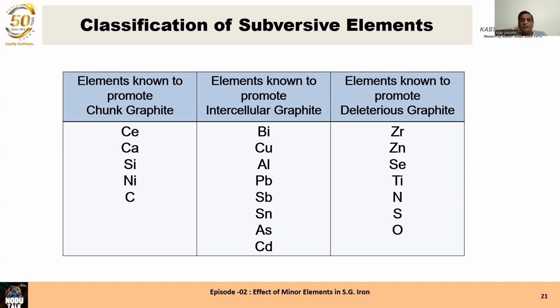Then the elements which are known to promote deleterious graphite, graphite which is affecting the mechanical properties, ductility and all the good properties of SG iron, are known as deleterious graphite. And the elements which promote this bad quality graphite are zirconium and zinc. Nowadays, all the cars are using zinc-coated steel for their undercarriage cover to prevent corrosion. And the zinc-coated scrap is very, very bad. As far as possible, do not use any zinc-coated scrap in your foundry.